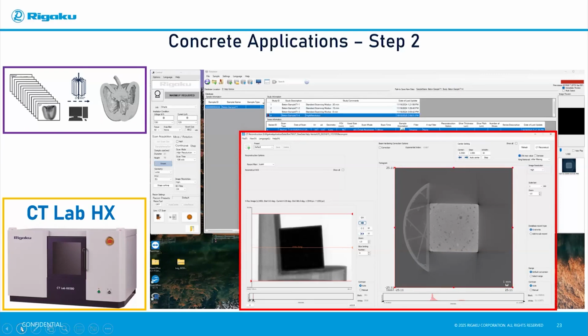An example is beam hardening correction, which is very important for many applications, including dense concrete samples. This effect occurs because X-rays are polychromatic, and different energies of the X-ray source are absorbed differently by the components of the sample. To compensate for these effects, the Rigaku software package implements tools for easy application of beam hardening correction by entering correction values. The CT operator can use different values for beam hardening correction and then compare different 3D reconstructions to determine which is the best for their specific application.